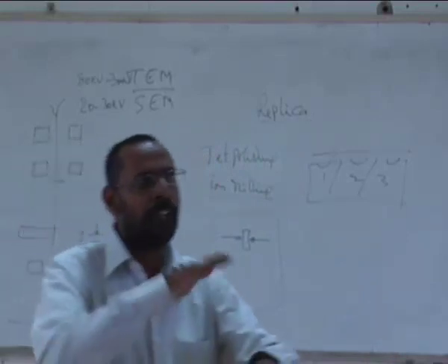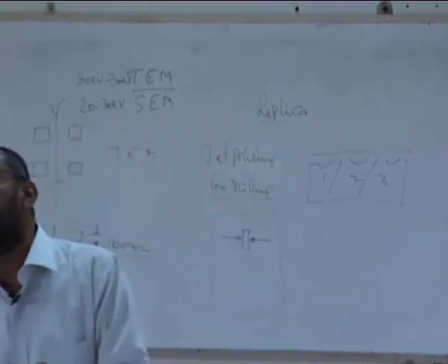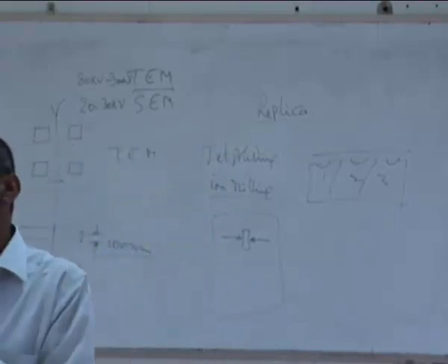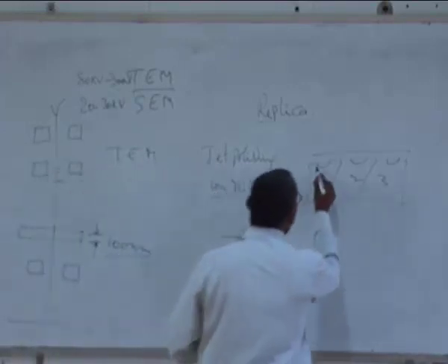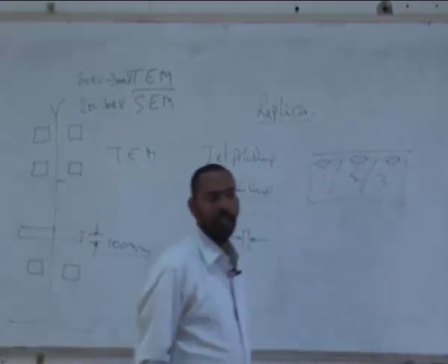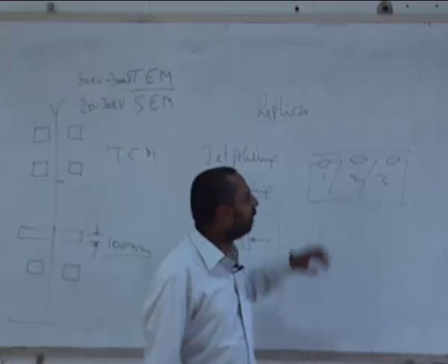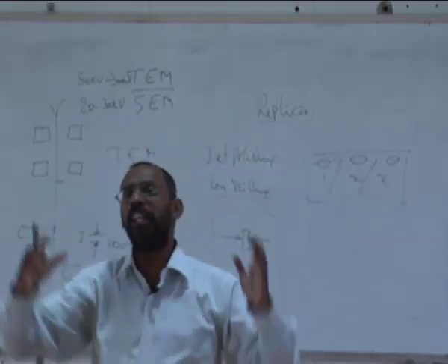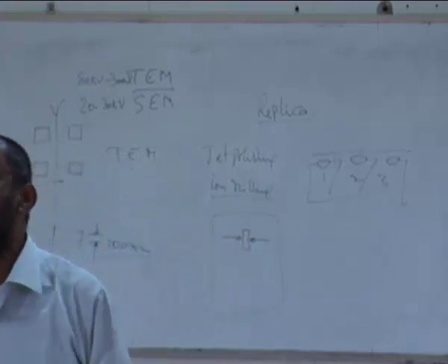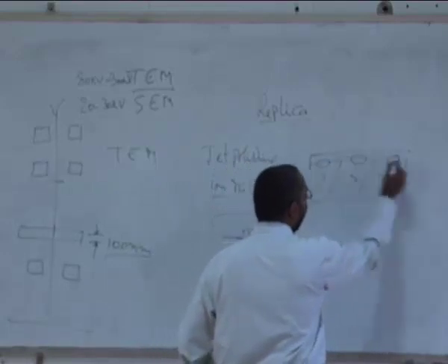So when you are polishing on an emery paper or even a cloth polishing at the final stage, you will see that the metal gets polished more easily, whereas these particles do not get polished. As a result, you will see that the particles actually protrude out because they are not polished. The metal is polished, so the particles are projecting out of the sample. And now what people used to do long back is to deposit a thin